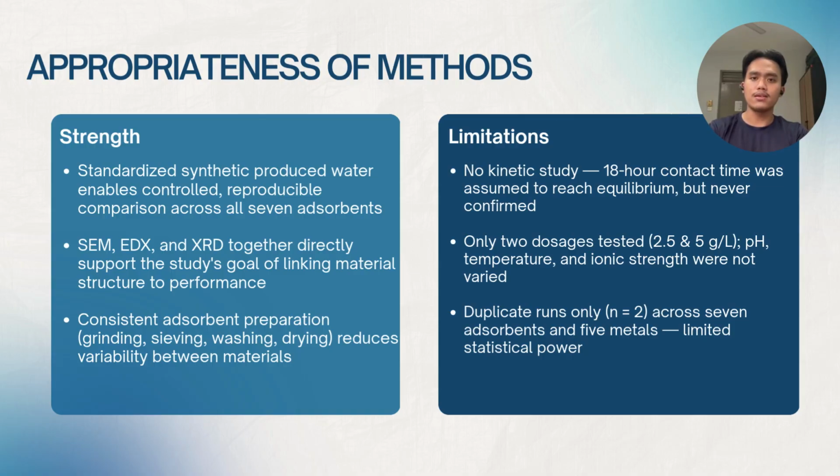So, for appropriateness of methods, the methods are largely appropriate. Using a standardized synthetic produced water allows for controlled comparison across 7 materials. The SEM, EDX, and XRD combination directly supports the study goal of linking material structure to performance. However, there are limitations. No kinetic study was done to confirm true equilibrium at 18 hours. Only 2 dosages were tested, and the sample size was just 2 replicates per condition, which limits the statistical confidence.